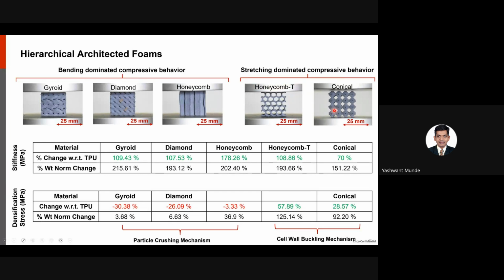Okay, so here we see that the stiffness, that is the initial slope of the load displacement response, increases for all of these as expected when we added GMBs. Here we have particularly considered the larger GMBs because of higher stiffness expectation. As I mentioned earlier, the bigger GMBs create a bridge between the segregated matrix and increase the stiffness, whereas the smaller GMBs, because of their higher crushing strength and because they are embedded within the segregated matrix, create higher densification stresses. With higher stiffness in mind, we use the larger particles to reinforce here.